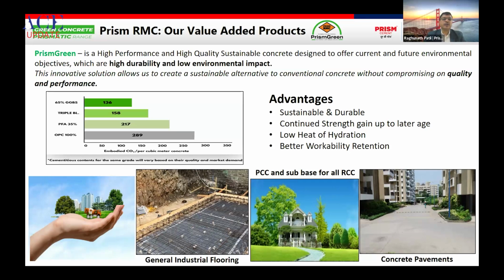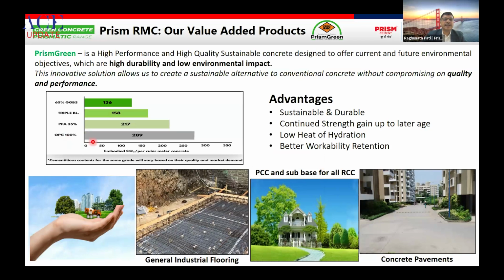Secondly, here we have shown one graph. So here we have shown the comparison. Suppose the grade of concrete is M30, and if you use only 100% OPC cement, the embodied CO2 is around 289 kg per cubic meter of concrete. But if you replace it with pozzolanic material, 35% fly ash gives 217, and with a higher amount of GGBS it is just 126. So we can reduce the embodied CO2 in the concrete by more than 50%.